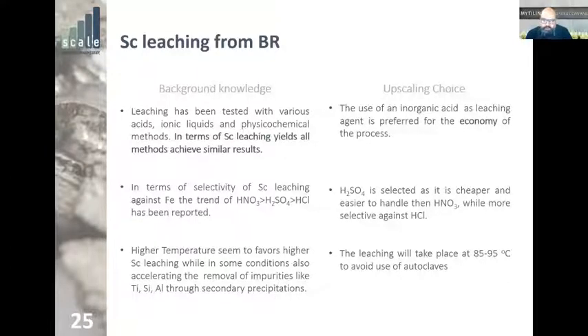Of course, for the sake of economy, for making a viable process, we don't want to go into autoclave leaching. Therefore, we go at the temperature range between 85 degrees and 95 degrees Celsius.